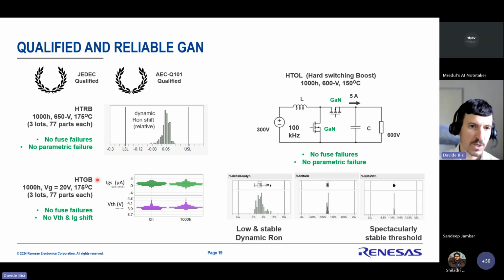I want to focus your attention on the high temperature gate bias. So these are 1,000 hours, 20 volts on the gate at 175 C. And again, we had no failures and no shift in the parameters, so no gate leakage increase and no shift in threshold, which is very stable at 4 volts.